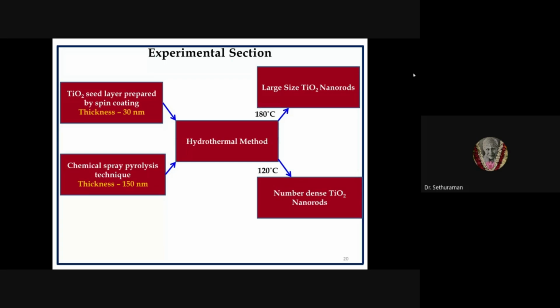The lower thickness TiO2 seed layer was used with 180 degrees, the higher temperature in hydrothermal, and we obtained large size TiO2 nanorods. The higher thickness seed layer was used for the preparation of TiO2 nanorods at 120 degrees Celsius, the lower temperature compared with 180 degrees Celsius. So 180 degrees Celsius nucleation temperature gives large size TiO2 nanorods, and 120 degrees Celsius gives number dense TiO2 nanorods on the surface of the glass substrate.